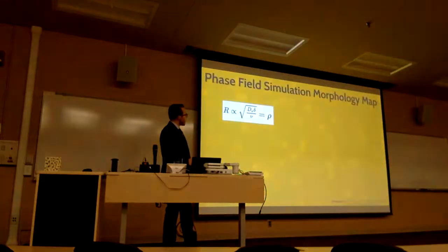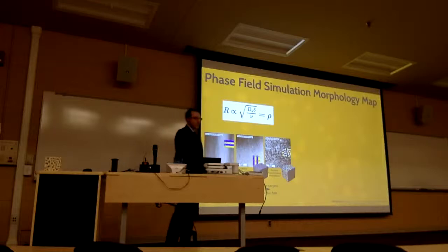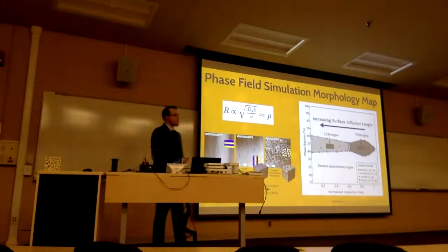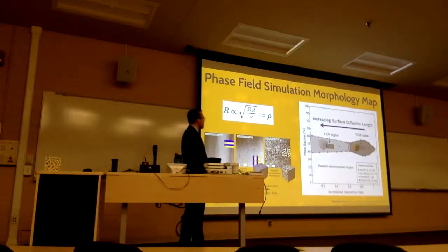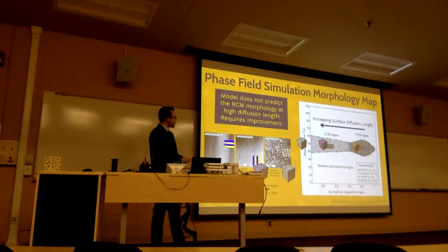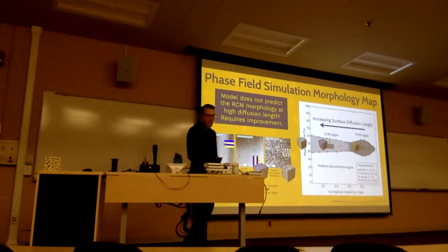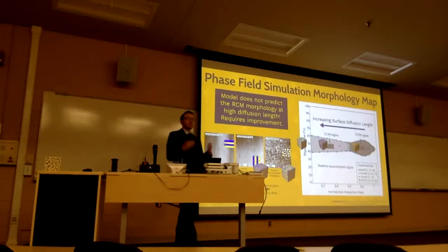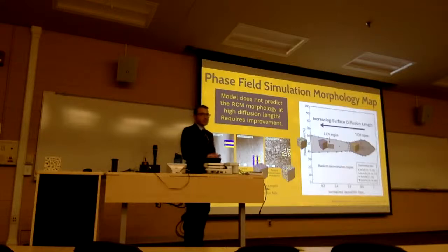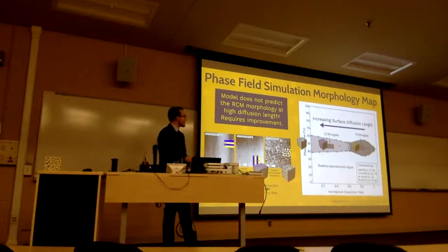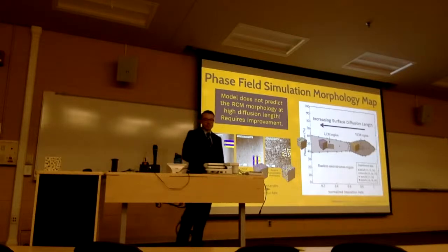But one thing you might notice is that our empirical results, based on the diffusion length, actually predict random concentration modulations at the highest diffusion lengths during deposition. But our morphology map only predicts 2 of those morphologies. So we can put the VCM and the LCM on there, but our empirical results suggest that the RCM should be to the left in that plot. And so this model doesn't actually predict that RCM-like structure. What's happening here is that the RCM structure is inherently 3-dimensional. This morphology map was done by a 2D phase field simulation. So we extended our model in 3 dimensions in phase field to actually form or predict this RCM-like morphology.